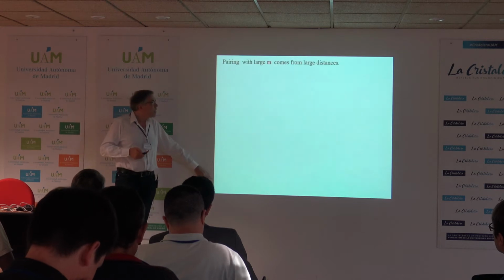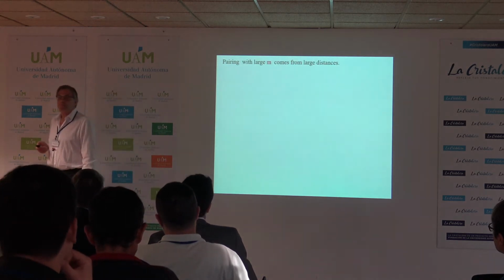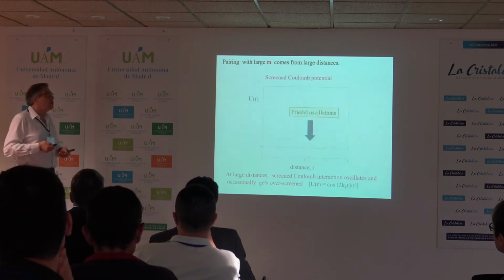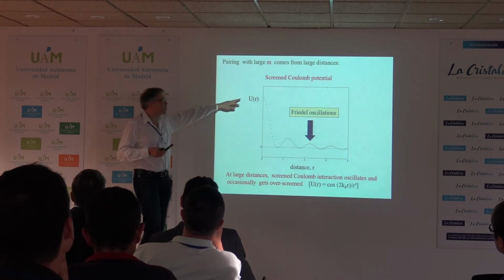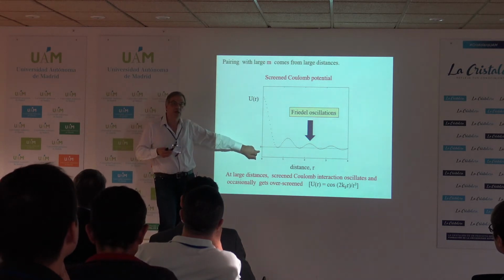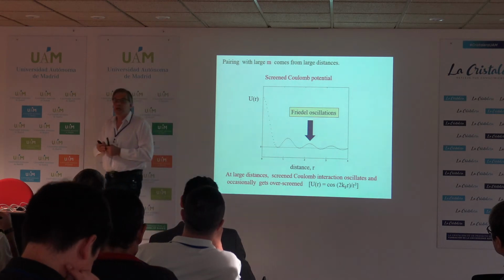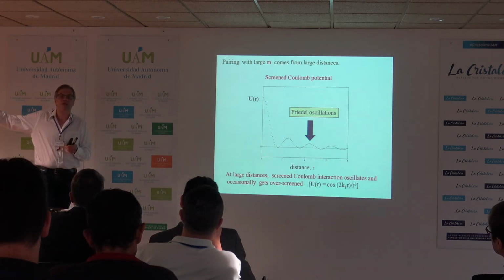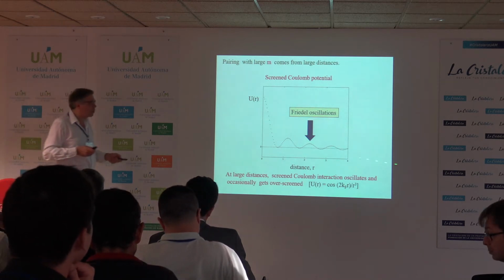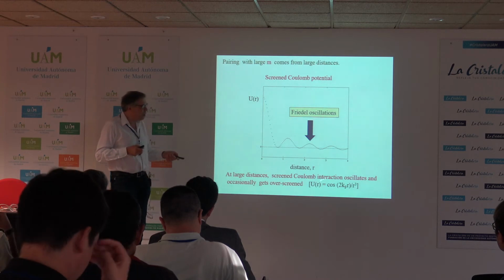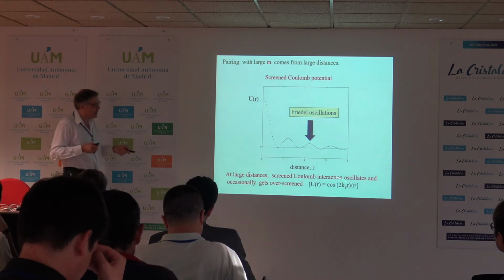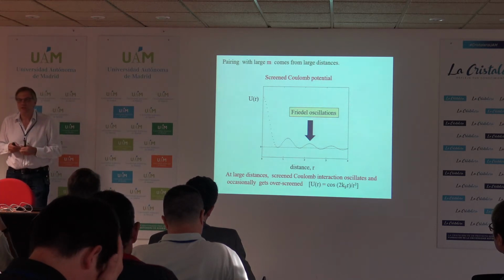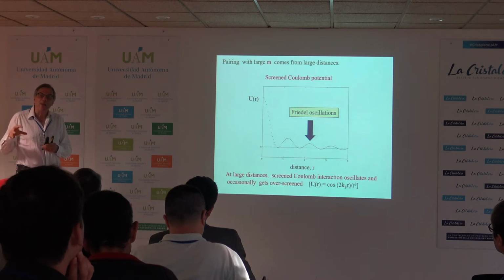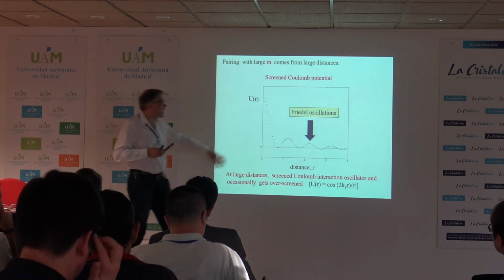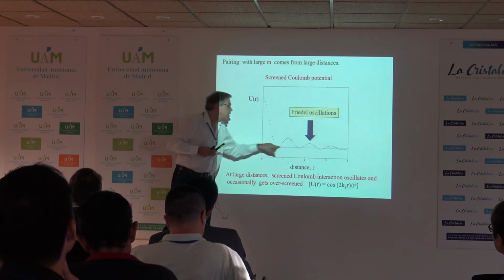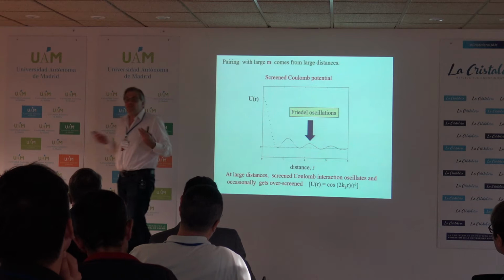Why is this relevant? Because if you take screened Coulomb interaction, and just open textbooks on screened Coulomb interaction, you find out that besides the standard story with Coulomb interaction transforming into Yukawa potential, this regular screening, there is something else. It's called Friedel oscillations. At large distances, screened Coulomb interaction necessarily oscillates. These oscillations, which are related to the sharpness of the Fermi surface, go normally in 3 dimensions as cosine 2 k_F r over r cubed, and they are known as Friedel oscillations. And if you look at this, you can say, well, this means that the screened interaction can occasionally be overscreened. In these regions, the interaction changes sign and becomes attractive.